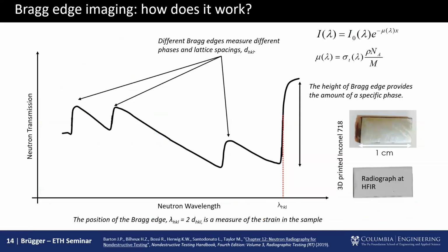Okay, so I mentioned Bragg edge imaging. What is this? Well, it turns out, as I've mentioned, if I have a sample in engineering materials diffraction, I hit it with neutrons, a few percent of those neutrons interact with the nucleus of the various phases of the material, and they shoot off, and we detect those in diffraction with diffraction detectors. And now you can imagine that means essentially there's that null space of those diffracted neutrons that if I now look at the transmitted signal, we're missing part of the signal. It's that part of the signal that before we were measuring.